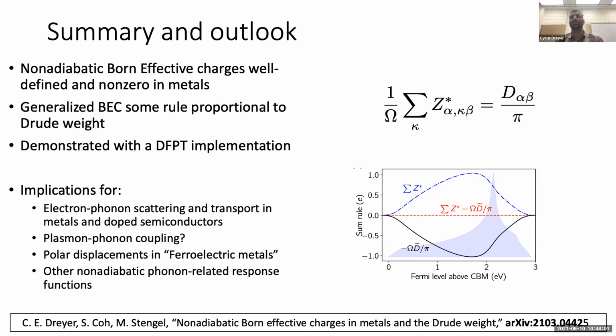Yeah, so that's a great question. With the rigid band approximation, you can quite easily also look at holes, and we did so for strontium titanate. It's not included, as you said, because it's not very physically relevant for that material. I think it will depend on the nature of the valence band, so where that positive charge is going to go. For example, in tin oxide or strontium titanate, the holes would be in oxygen p states. And so the Born effective charges for the oxygen sublattices would probably change more significantly.